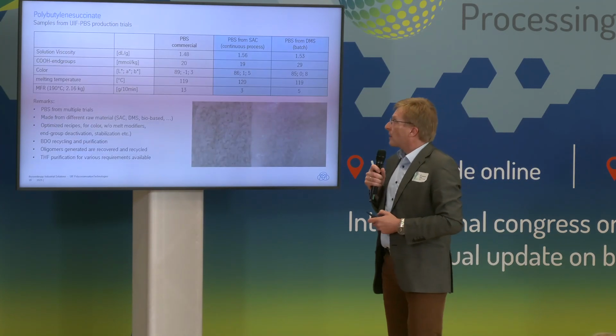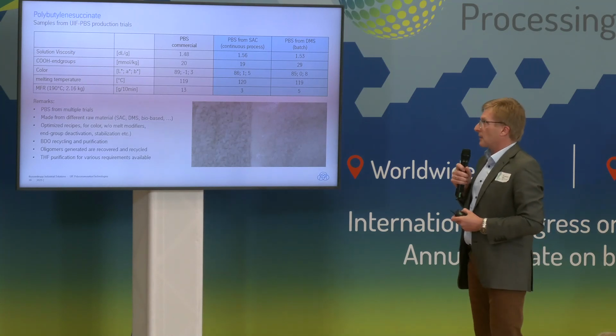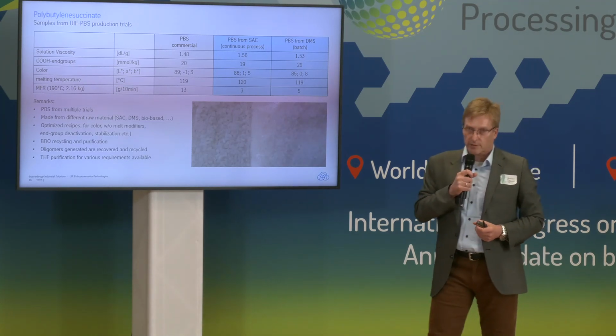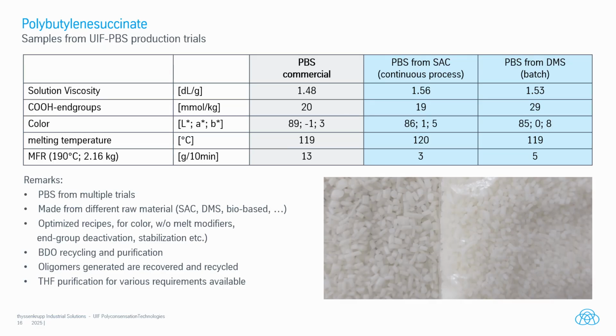So, and this is also more or less my final slide. These are some trials we have done in Berlin in our continuous pilot plant as well as batch plant. We have made PBS from succinic acid continuously. We have made PBS from DMS in the batch process. And if you compare the values of the PBS we have produced to commercial grades, which are already available, we see that if you produce PBS to our recipe with our plant, we are more or less exactly where the existing PBS grades are. So these are more or less my remarks.